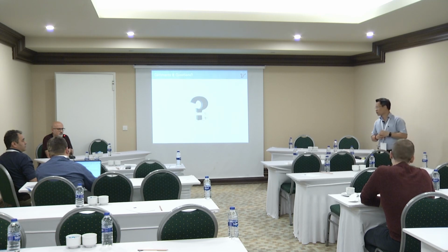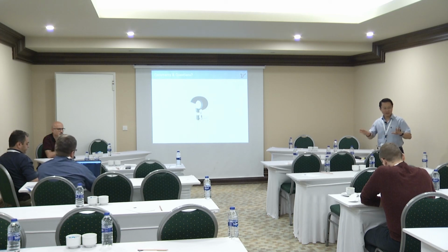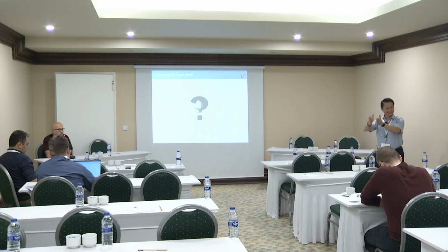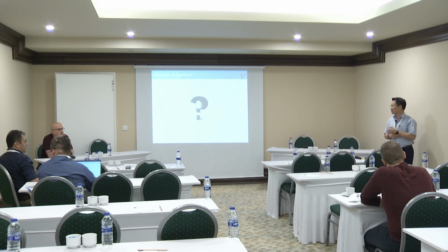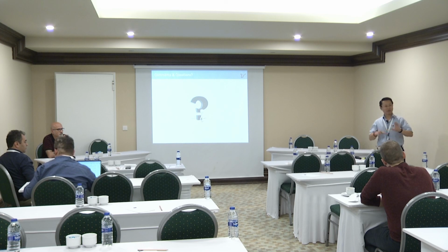We also looked at a completely different system, not VSe2. It's just TiSe2, which is non-magnetic. When TiSe2 has defects, that is also kind of a defective interface, and we also observe the exchange bias. So it turned out to be very interesting. It's kind of a combination. That's why this system is interesting to explore both the exchange bias and the magnetic proximity effect.